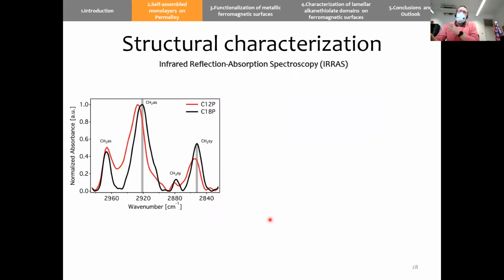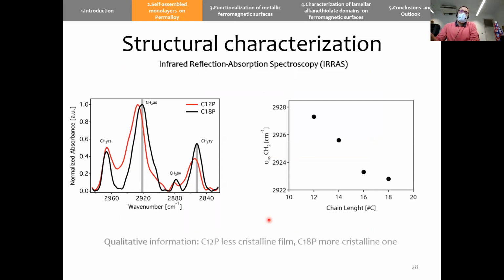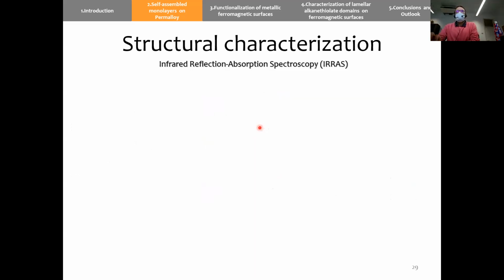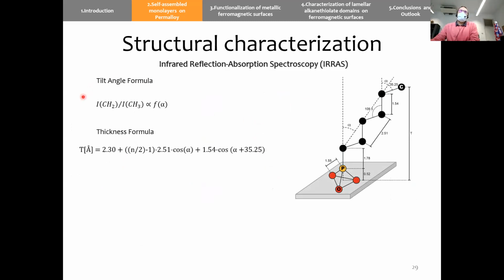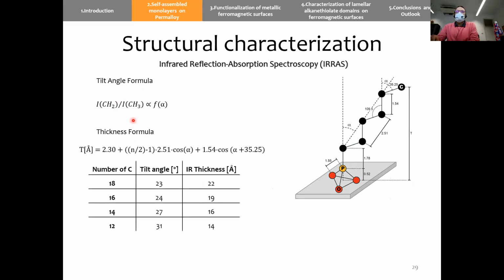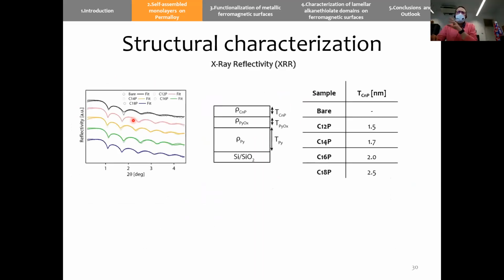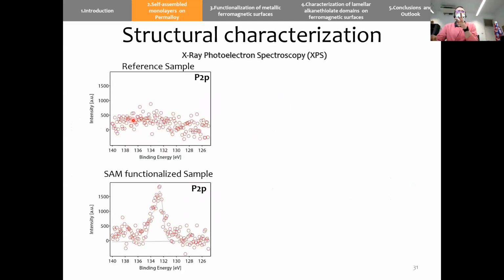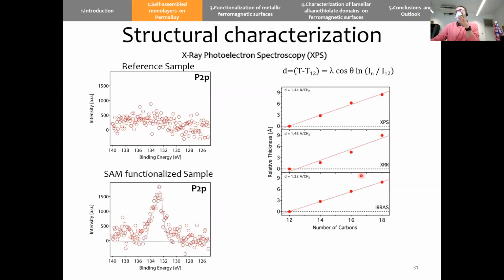By infrared, we can obtain qualitative information: thanks to the shift in frequency of the CH2, we can attribute a more or less crystalline film. And quantitatively, by studying the intensity of the CH2 and the intensity of the CH3 associated signals, we can also calculate the tilt angle. So what we observe qualitatively, we can also get as quantitative information. Again, we checked with X-ray reflectivity, and finally, we also checked by XPS. We see that we have a good agreement between 3 different techniques, and we are sure that we could grow this SAM.